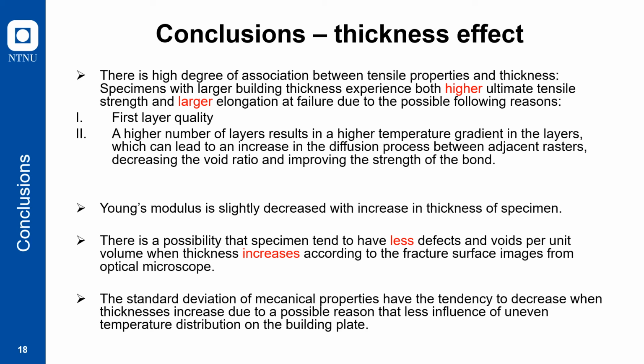And the standard deviation for the mechanical properties has a tendency to decrease when the thickness increases. So there's less discrepancy in the data, possibly because uneven temperature distribution on the building plate will have less influence. For the specimen fabrication, we have 5 specimens for each case, and we fabricated 5 of them on the same plate, so there might be some uneven temperature distribution on the plate, which may cause the discrepancy of the data. And when the thickness increases, the influence of that gets smaller.